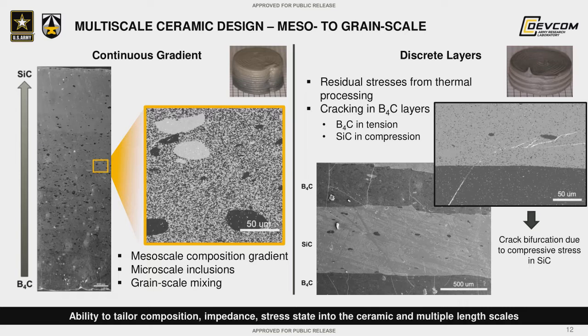So you can see in the blown up microstructure image, you do get a good amount of microscale mixing between the individual boron carbide and silicon carbide grains, which are about a micron length scale. But you also have these large agglomerates of boron carbide and silicon carbide, which have not been fully broken up. On the discrete layers, you can see that we have a very sharp interface between the boron carbide and silicon carbide layers, but we can also note a lot of residual stress-induced cracking from the coefficient of thermal mismatch between boron carbide and silicon carbide during processing, which is undesirable in the final components because that will reduce the mechanical properties of it.